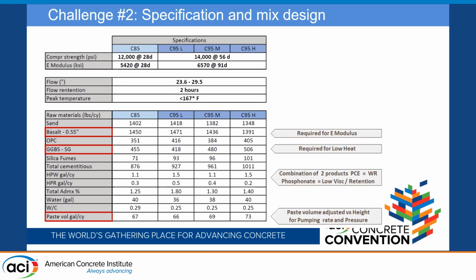Another thing to point out on this slide is, I'm going to talk about the tribometer shortly, but through this process, we identified that the admix, the superplasticizer, the high range water reducer, was extremely critical to how those particles moved and how it coated the particles in that mix. If you use the wrong high range water reducer, they're not all created equal. If you use the wrong one, you're not going to have the right lubrication. You're not going to have the right movement, and it would make it really difficult to pump. So we came up with some new technologies that I'm going to talk about to really isolate what is going to be the best superplasticizer to use, what is the best slag to use, and so on.